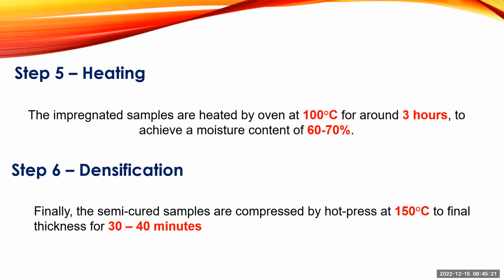After that, the next step, the impregnated sample will be heated again in the oven at 100 degrees Celsius for around 3 hours to achieve a moisture content of 60 to 70%. The last step will be the densification. So the semi-cure, after the heating in the oven, the sample will become semi-cured and it will be compressed by a hot press at 150 degrees to final thickness for 30 to 40 minutes.